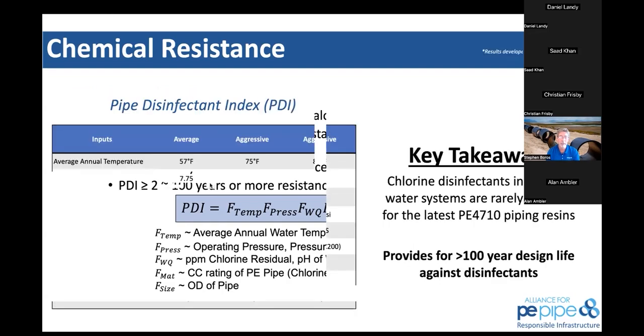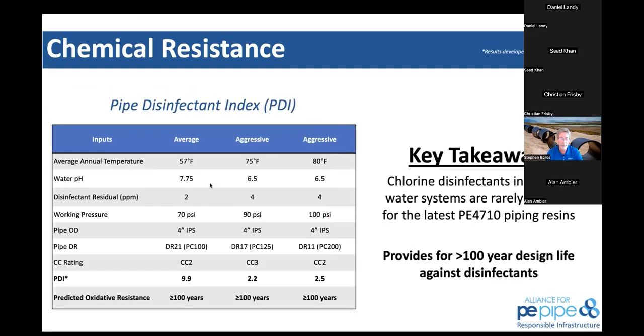And if you look at the next slide, you can see here that by taking these general factors and looking at general operating conditions. So for the average across the United States, 57°F average annual temperature, water pH 7.75, disinfectant residual 2, 70 PSI working pressure. You can see that even a DR21 polyethylene pipe using a mid-range, a CC2 rated polyethylene, has greater than 100-year resistance to chlorine. Not going to be an issue.